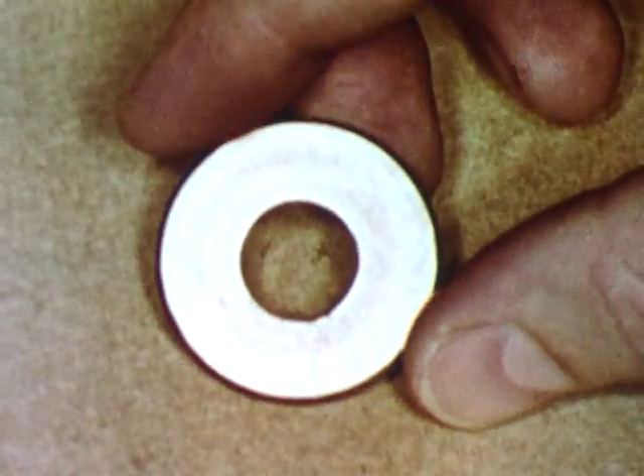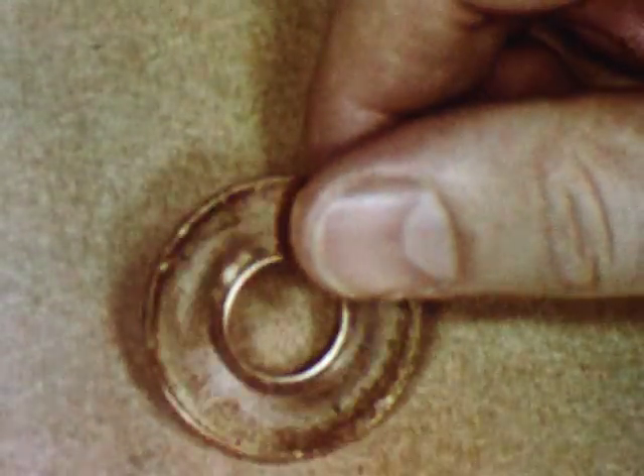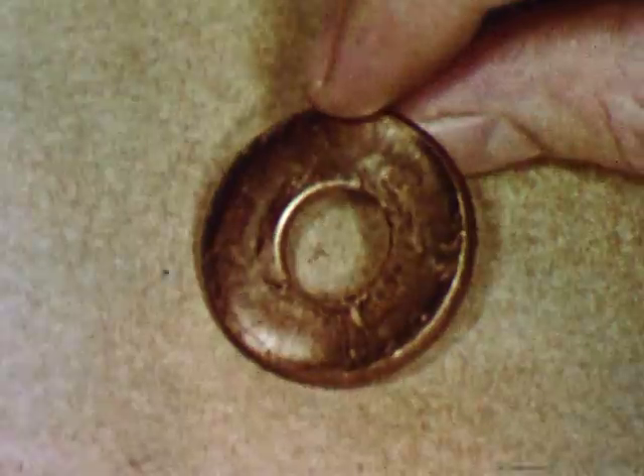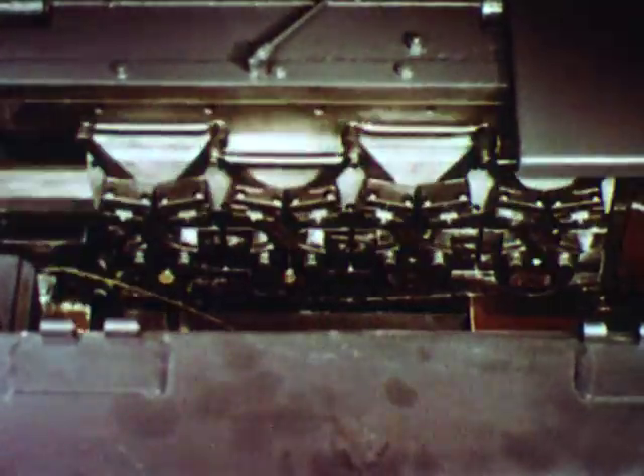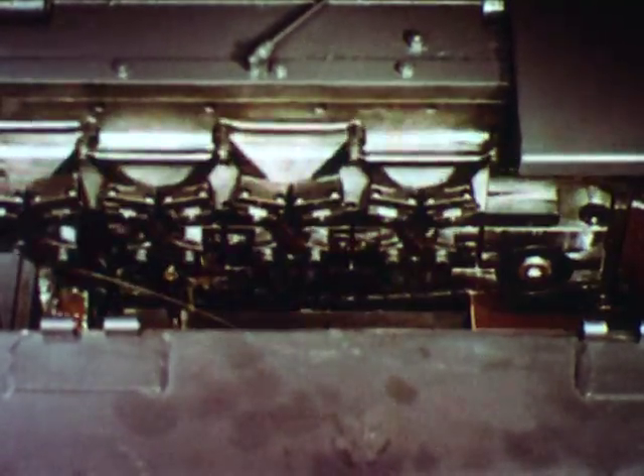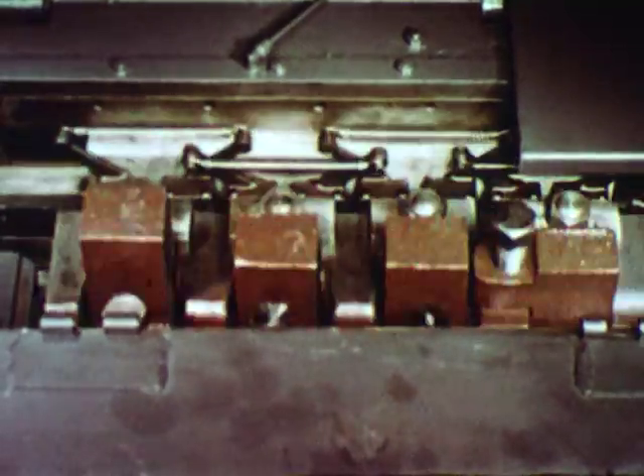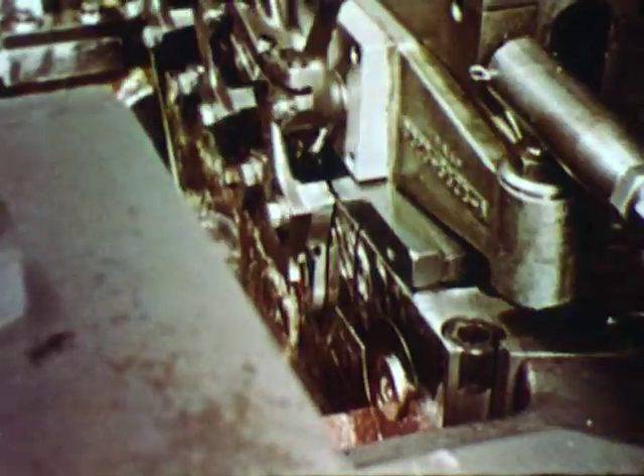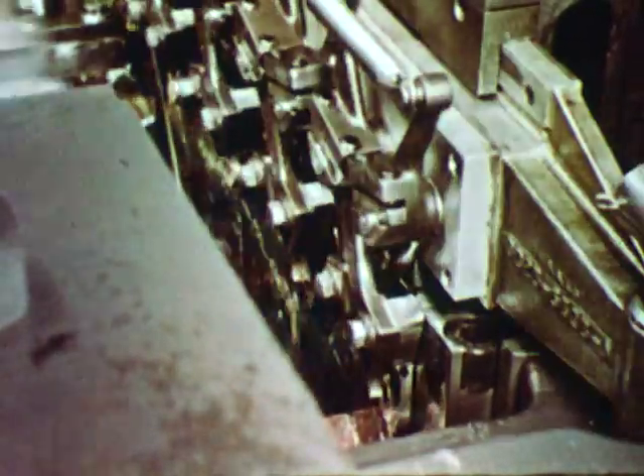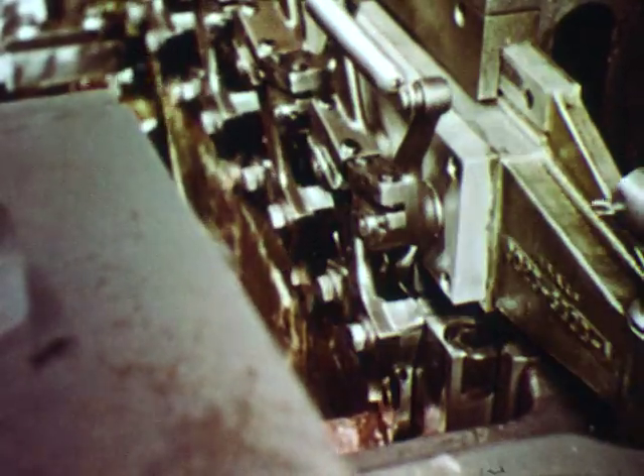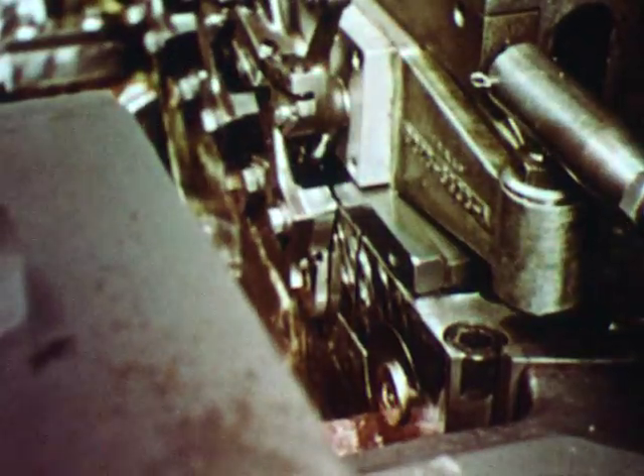Some parts do not require pointing or threading, like this starter solenoid contact made on a 1/2-inch 4-die progressive header from pure copper wire at 90 per minute. A progressive header is basically the same as a bolt maker, but without pointer or roll threader. In 3 dies, the wire is upset from 5/8 of an inch to 1 1/4 inches. Prior to cold forming, these parts were stamped from copper sheets with over 32% scrap. By cold forming, scrap loss is only 12%. In the last station, the center is punched out and the slug is discharged through the bottom of the punch holder.